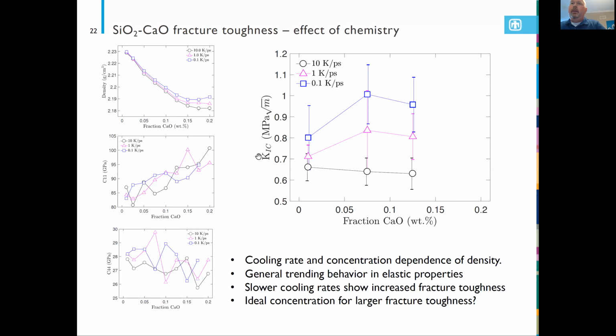If we look at fracture toughness here and note there's only 3 points, I know that 3 points don't necessarily make a trending type behavior here. But in terms of cooling rate, again, we see greater fracture toughness with decreasing cooling rate, slower cooling rates, sorry. And if you follow or agree with this 3-point trend, hate to say that, it suggests that there is a concentration of calcium that gives rise to the greatest fracture toughness.